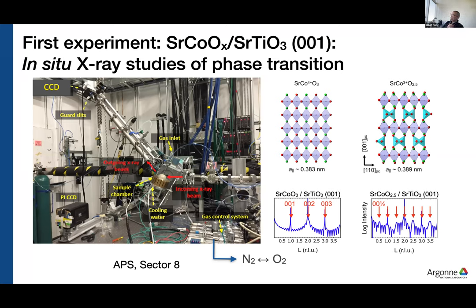One of the reasons why I like this system so much is because the strontium cobaltite perovskite phase has these integer Bragg peaks: there's a 1, 2, and 3. When you switch to the Brownmillerite phase, because it's made of these layers of oxygen octahedra and oxygen tetrahedra, you double the repeat unit in the out-of-plane direction. So in reciprocal space, you get these half-order reflections, like 0.5. And so we can just watch the phase change in situ by watching the 0.5 come and go.